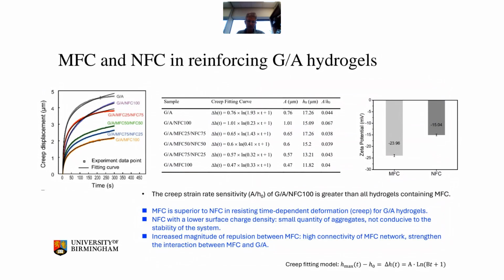without the cellulose in there, that hydrogel is susceptible to creep. If you put some nanofibrillated cellulose into that, it improves things, and if you put more microfibrillated cellulose into that, it improves the creep resistance more and more, which is a very useful design improvement. And Jason wondered why that was, and he did some surface science measurements. There are measurements of zeta potential there, and you can see that the nanofibrillated cellulose is at the point where you're getting some agglomeration, which is not helping, but there's more stability with the much bigger and stiffer microchains.